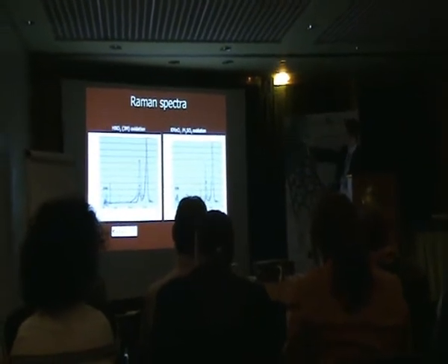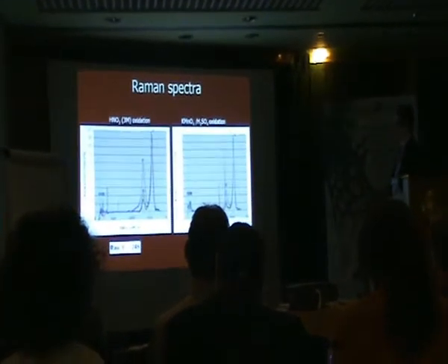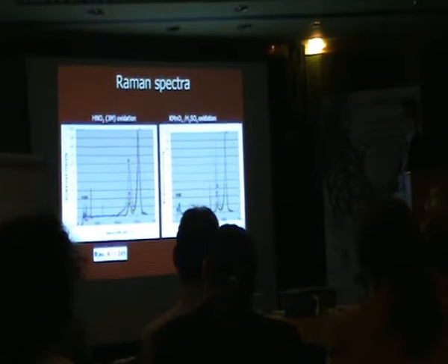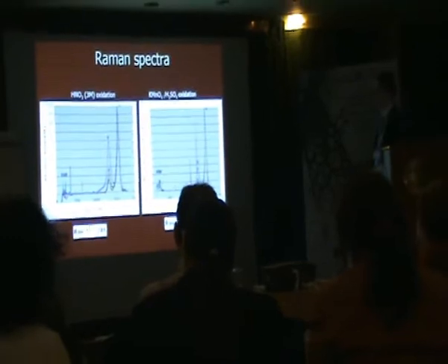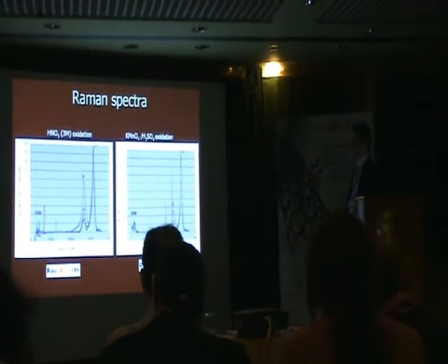Also, we have Raman spectra of the same samples, oxidation with 3 molar nitric acid. What we can see in blue is the spectrum after 24 hours of oxidation, and we can say that the defects in the structure after 24 hours of oxidation are much more than in the raw carbon nanotubes and after oxidation for 3, 6 hours and 9 hours.